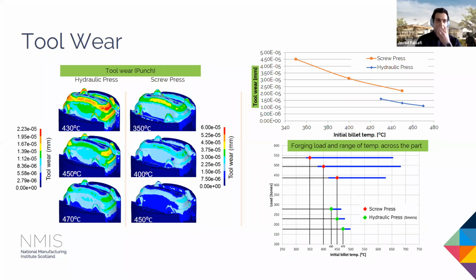Forging load also is shown here at various initial billet temperature, and the final range of the temperature is shown with that blue line across the part. So in case of the screw press, we can see that there is a significant amount of adiabatic heating across the part, and the range of temperature is very wide. So one of the things that was important for us was to avoid any melting. Because of that, we can see that 450 is quite a suitable temperature for the screw press, and obviously for the hydraulic press, it's fairly straightforward. Any of those temperatures would do.